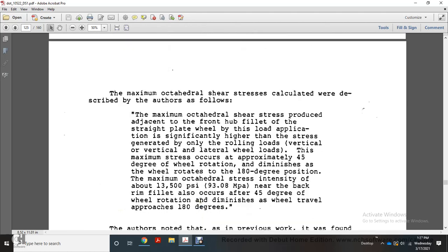Maximum octahedral shear stress was calculated, as the authors followed. Maximum octahedral shear stress produced adjacent to the front hub fillet over the straight plate wheel with the load applied was significantly higher than the stress generated by only the rolling loads, vertical and lateral wheel loads. This maximum stress occurred at approximately 45-degree wheel rotation and diminished as the wheel rotated to the 180-degree position.